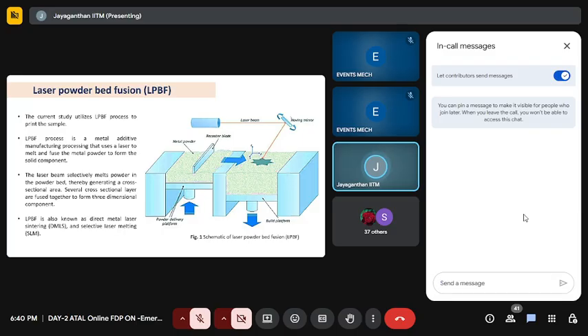Having qualified the powder, you do 3D printing of the material test coupon. The test coupon data needs to be generated by doing testing, static test and dynamic test. Static test, you are aware, you have a UTM machine. The UTM machine you have to use to do compression strength and tensile strength tests, fracture toughness. You might all be aware, you may be conducting strength of materials classes for the students and in your lab also. How you get material hardness, tensile strength, ultimate tensile strength, fracture toughness.